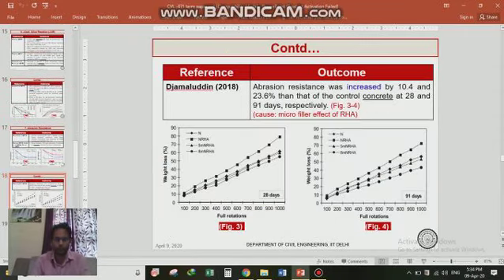In 2018, Jamaluddin concluded that abrasion resistance was increased by 10.4 and 23.6% compared to that of controlled concrete at 28 and 91 days, which was due to the microfiller effect of RHA. So here we can see that.